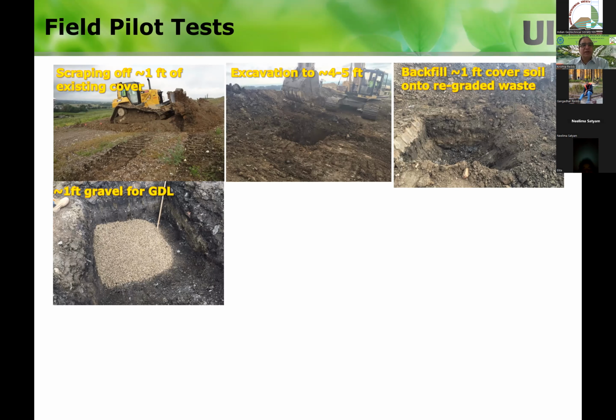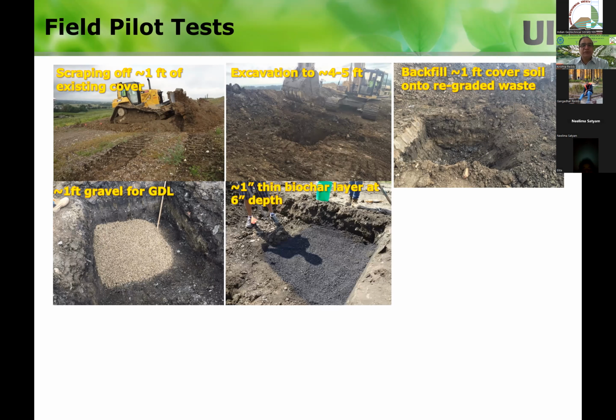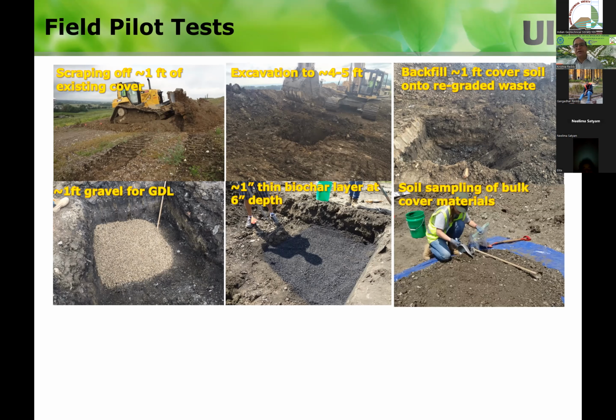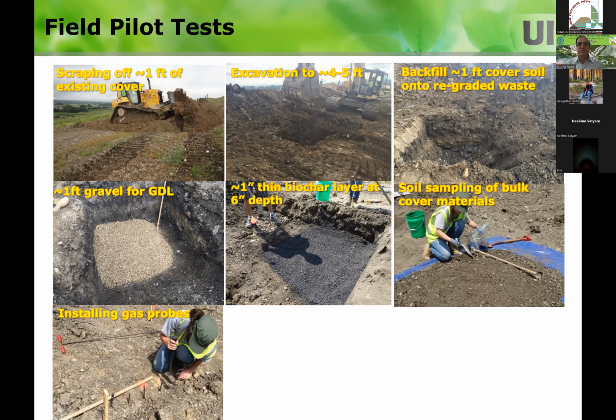So then we put a gas distribution layer, gravel at the bottom, and then we put either soil amended with the biochar, or the biochar layer, thin layers amended. We just mix the biochar and the soil, and we found that it's easily mixable. Mixing is the biggest challenge. We could use the tilling equipment, conventional gardening equipment, to do all the work.